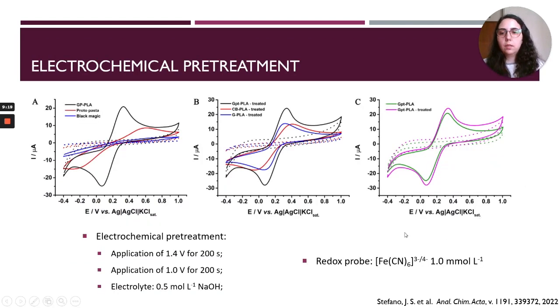As I mentioned, the main feature of this filament is that it does not require any electrochemical pretreatment, just some sanding to remove the grooves from the 3D printed electrodes. So what we did here is we compared the performance of the developed filament with the ones already present in the market. We did this with and without electrochemical pretreatments. The electrochemical pretreatment applied was using NaOH and applying some fixed voltages for 200 seconds.